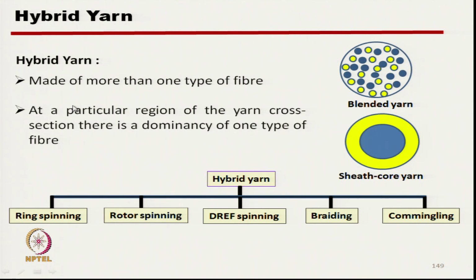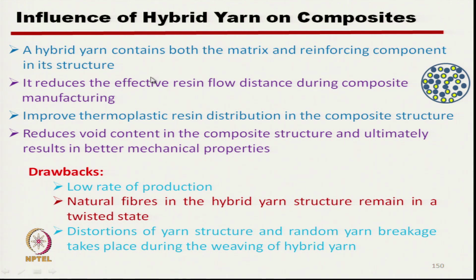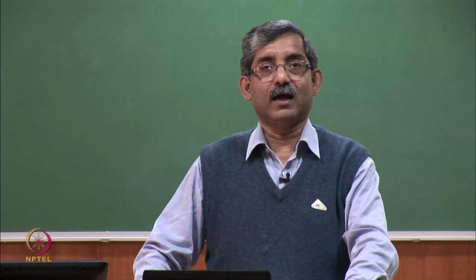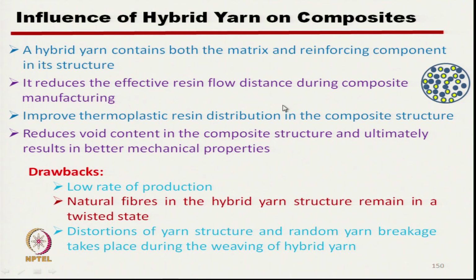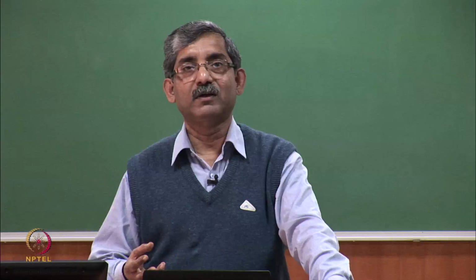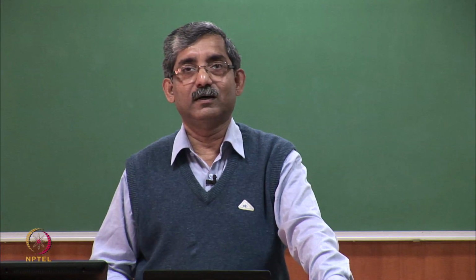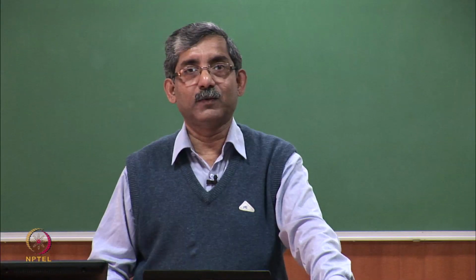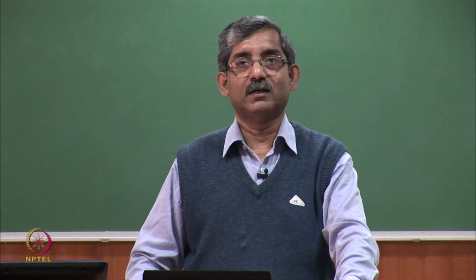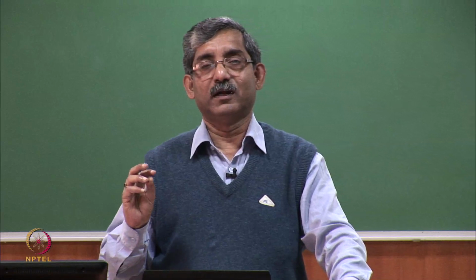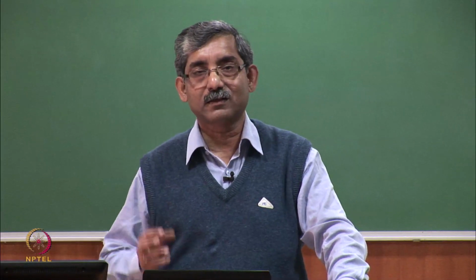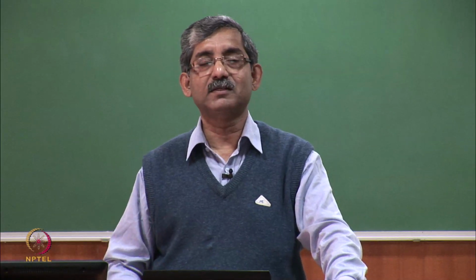So, basically hybrid yarns are yarns where more than one component is present. A hybrid yarn contains both matrix and reinforcing components within the structure, and it reduces the effective resin flow distance during composite manufacture, which is very important because thermoplastics have very high melt viscosity. The hybrid yarn improves thermoplastic resin distribution in the composite structure, because both the reinforcing fiber and the thermoplastic matrix fiber are already present inside the structure.